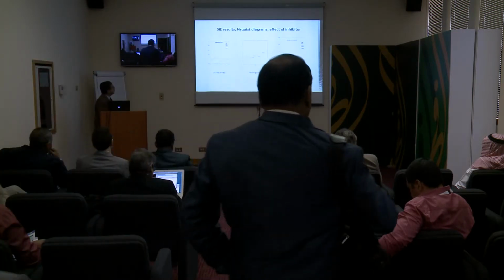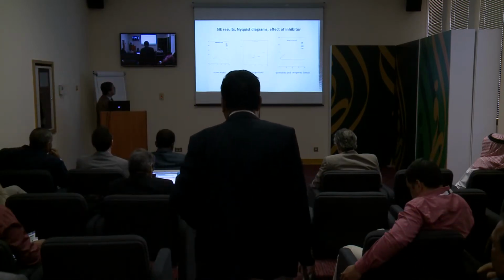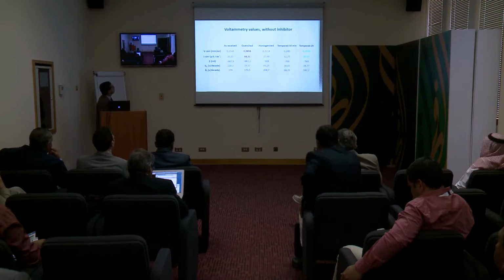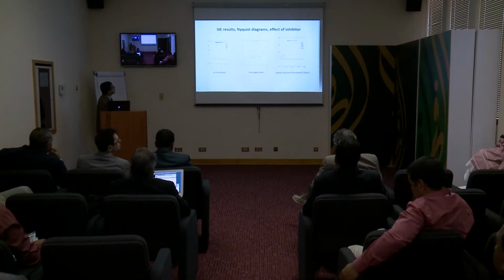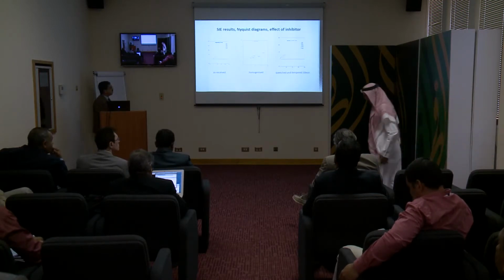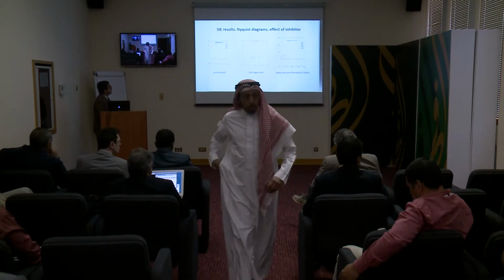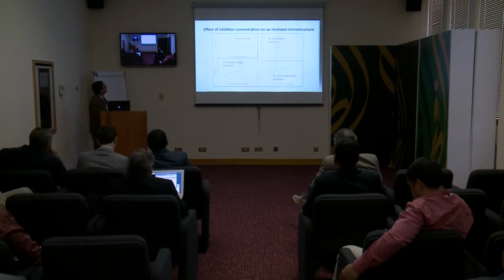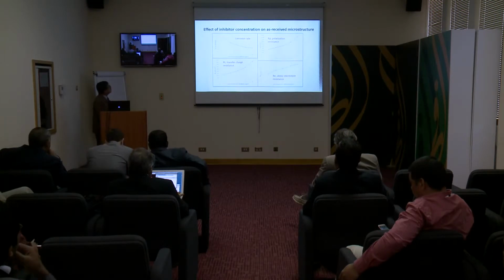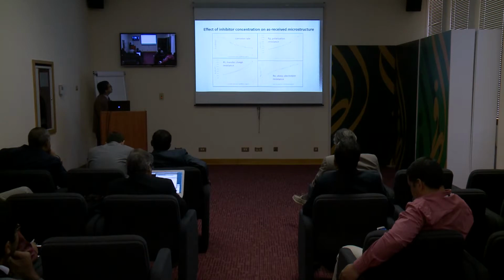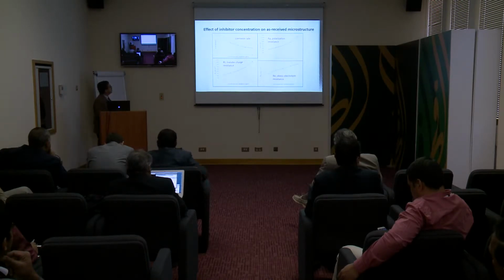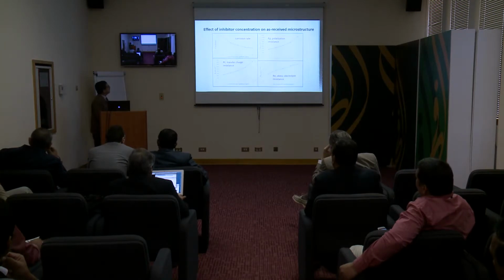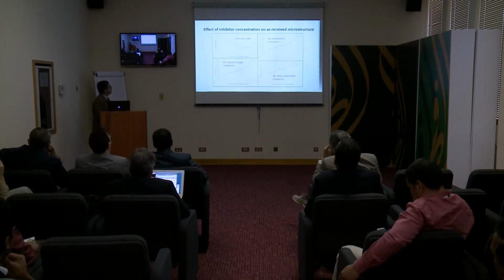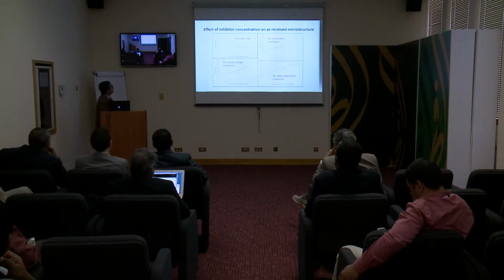The results in impedance indicate in all cases that we have a higher polarization resistance, and also a higher charge transfer resistance. We have here presented on the first microstructure all the results of corrosion rate with increasing inhibitor concentration, the polarization resistance, charge transfer resistance, and ohmic electrolytic resistance, which indicates that each time we increase the concentration of inhibitor we get a better resistance. That's for the as received one.